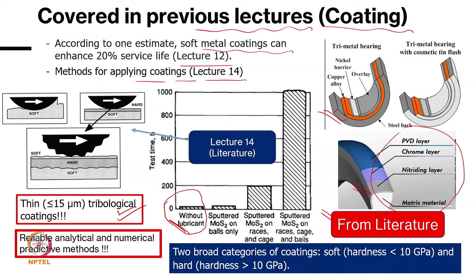In this case, without any solid lubricant like MoS2 as a coating, we get some performance. The performance gets better for the ball bearing when MoS2 is sputtered on the balls. The performance is almost 2 to 3 times improved. When we sputter MoS2 on the races and cages, but leave the balls as they are, performance increases almost 10 times. Now, when we sputter MoS2 on almost every element, performance increases significantly. And that's why we say coating is very important these days.